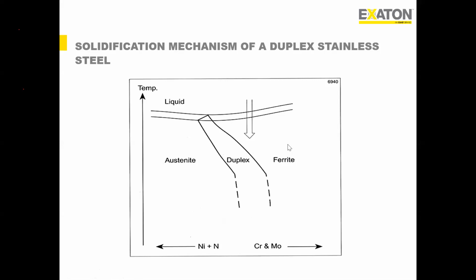Now, two very important factors play a role in how we are going to get a duplex structure. Number one, how much chromium and molybdenum is in our base material or in the filler metal? Because chromium and molybdenum are basically ferrite stabilizers. So these two alloy elements always try to hold the structure in the ferritic phase. On the other hand, we have nickel and nitrogen, and these two are basically austenite stabilizers. So these two alloy elements try to pull the structure from ferrite to austenite at room temperature. So it is basically a synergetic effect of these four most critical alloy elements, and they try to